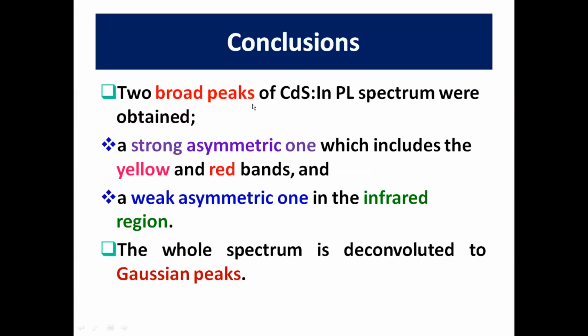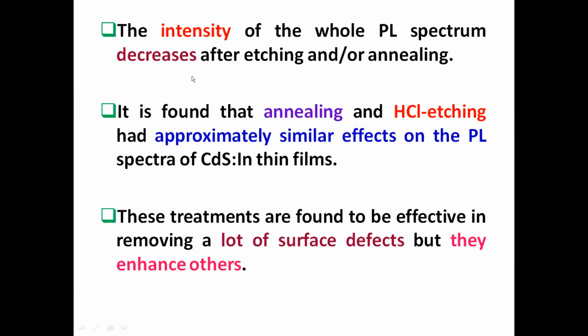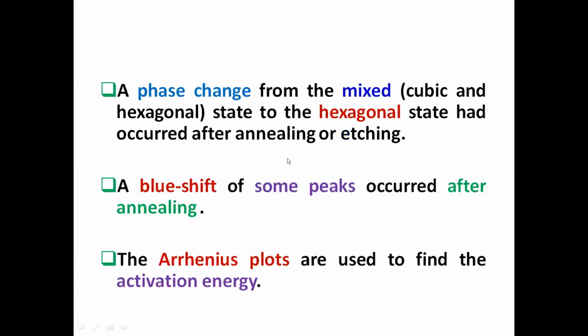Conclusions: 2 broad peaks were obtained, one asymmetric in the yellow-red and one asymmetric in the infrared. They are deconvoluted into Gaussian peaks. Intensity of PL decreases with etching and annealing. Annealing and etching have approximately similar effects. These treatments remove most of the defects, and a phase change from mixed phase to hexagonal phase occurred after annealing and etching. A blue shift of some peaks occurred after annealing. Arrhenius plots were used to find activation energy.